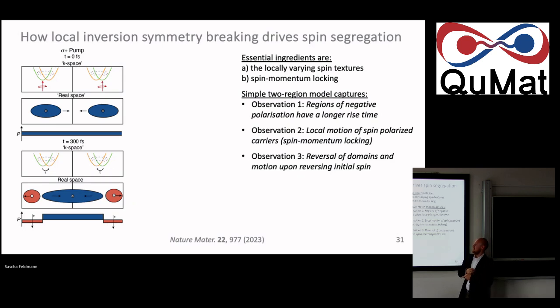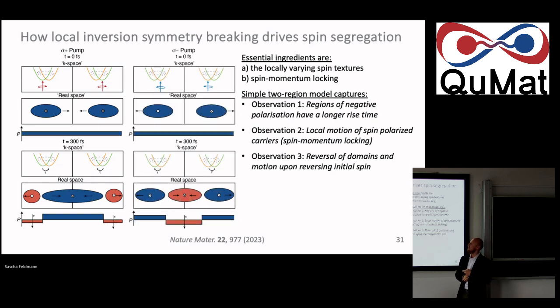And this is exactly what we see. So after some time delay, after the spin scattering has occurred, we therefore get this polarization pattern to develop. And of course, if you then switch just the initiation, so you just go to the other handedness of pump, so say from right to left-handed, then everything changes. So your initial rule of the game is maybe to go this way, but then after a spin flip, you will go to the other direction, etc. And the global pattern subsequently changes, flips. This is all it takes, really.